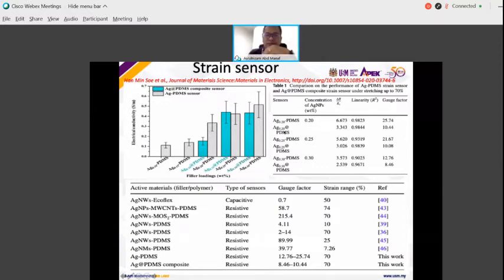We consider the weight percentage of the particles. For example, here the PDMS with 0.20% of the particles, or 0.25. So this is the mix ratio of the silver nanoparticles and the PDMS, to improve the conductivity. From that study, we have two types: the PDMS composite, and the silver with PDMS.